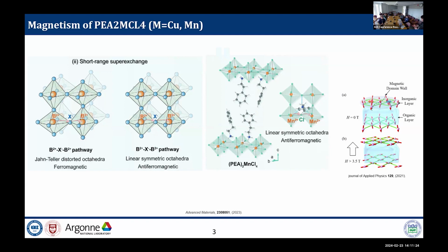so there is no Jahn-Teller distortion, but due to the distorted octahedral, the spin is canting. In this figure, you can see in-plane canted antiferromagnetism and weak ferromagnetic ordering due to the magnetic domain wall. This magnetic domain wall can be explained with the Dzyaloshinskii-Moriya interaction of the manganese-manganese antiferromagnetic ordering. Also, due to the spin canting, there is a spin flop transition at 3.5 Tesla in PEA2 manganese tetrachloride.